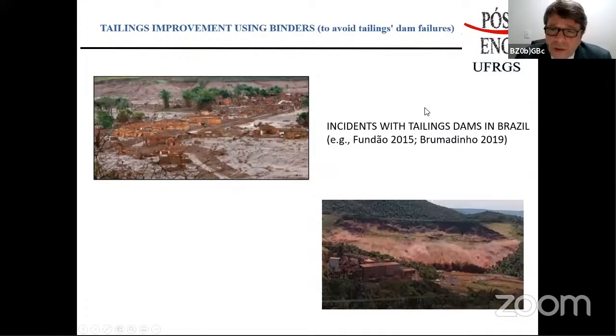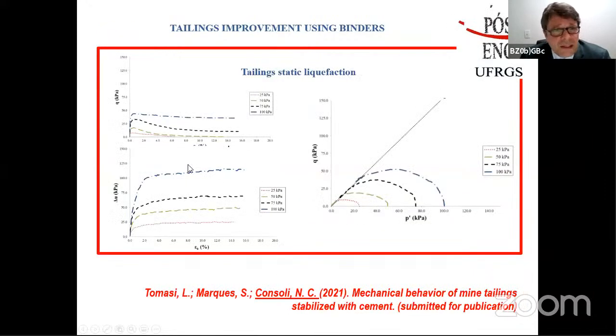Here, I would like to come back to the tailings failure. We see here the failure of the Feijão Dam in Brumadinho in 2019. Here, the results of the failure that we had previously in Mariana in 2015, the Fundão Dam. And we can see that the results are extremely bad. Looking at such results, of course, several people are looking for solutions. Many people have already researched the liquefaction problem that is shown here. In this case, for some gold tailings, specifically not iron tailings, it shows that for small confining stresses, you might have liquefaction occurring.